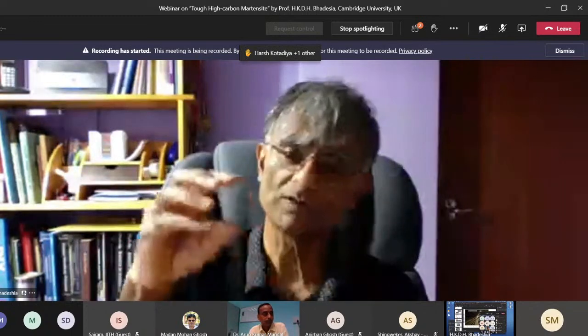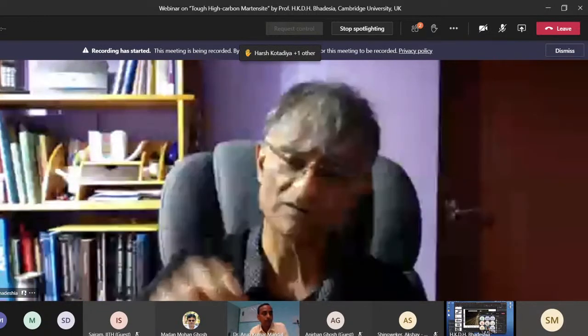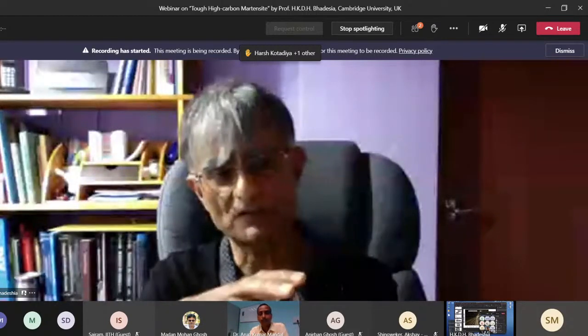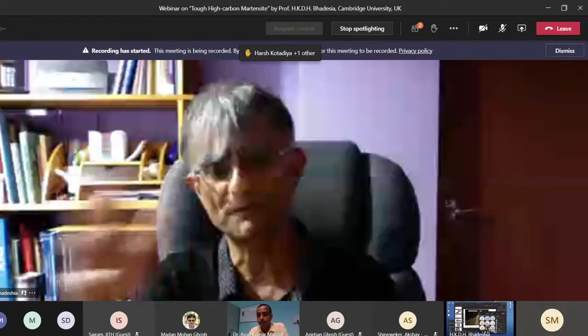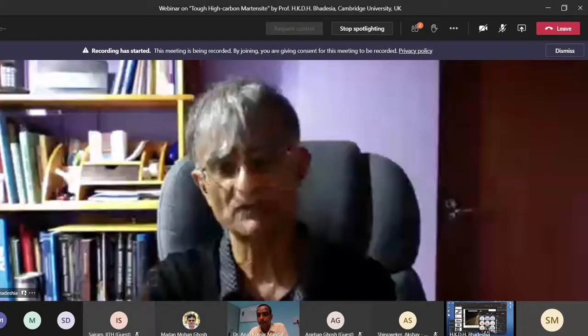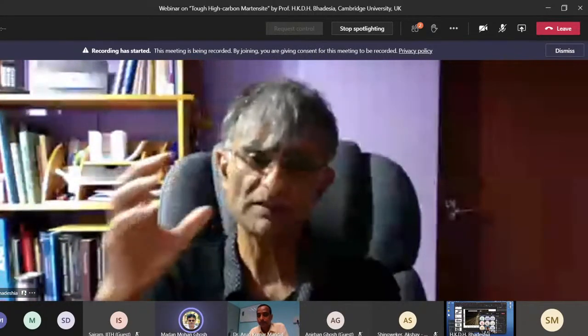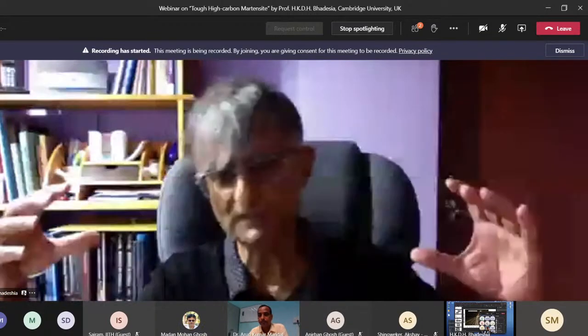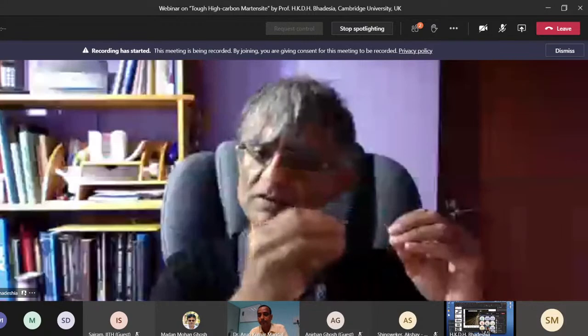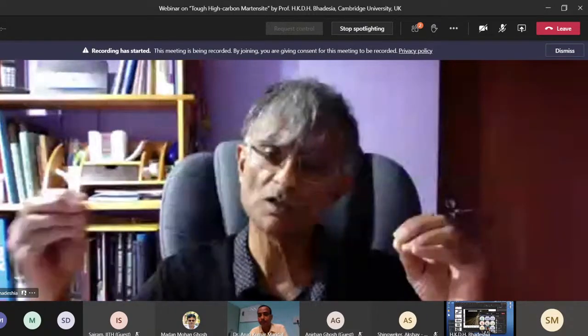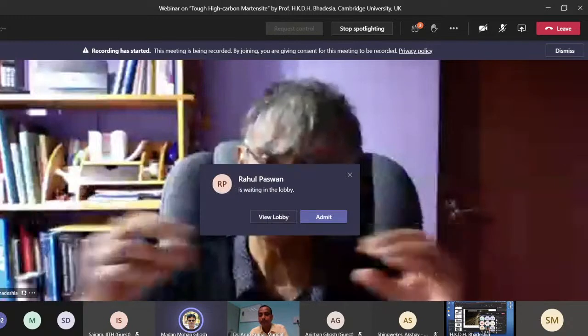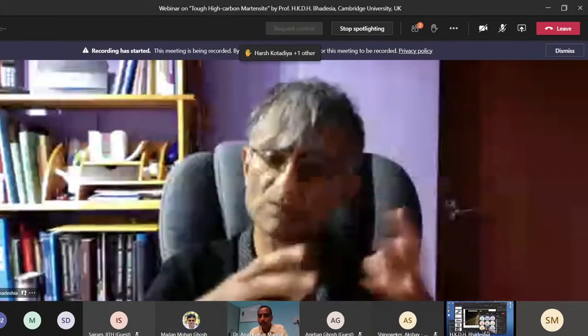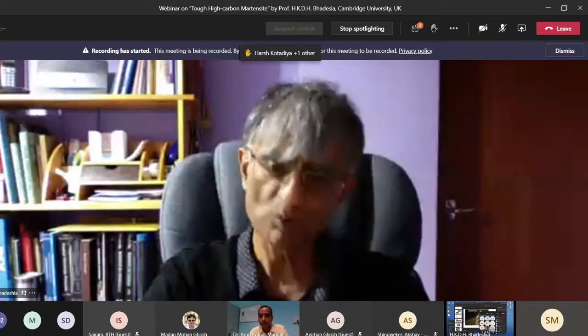Because I said to you that fracture occurs when you're actually loading the martensite. The austenite has lost percolation. But if you have a structure in which you have lots of allotriomorphic ferrite and bainitic ferrite and then retained austenite, then the fraction really depends on the application. If you want formability, then you want austenite which is going to decompose steadily over a large range of strain so that you maintain the work hardening that's necessary to prevent plastic instability. So elongation would then determine how much austenite you need, but it will be more than 10%.